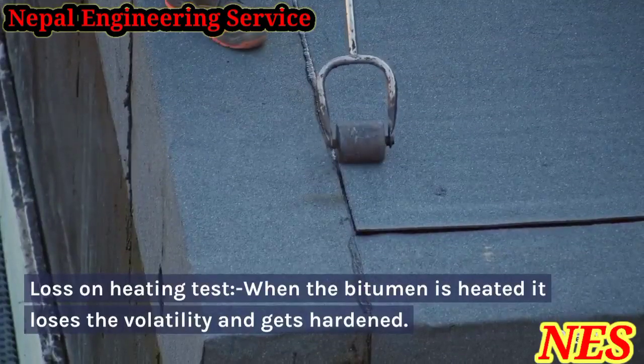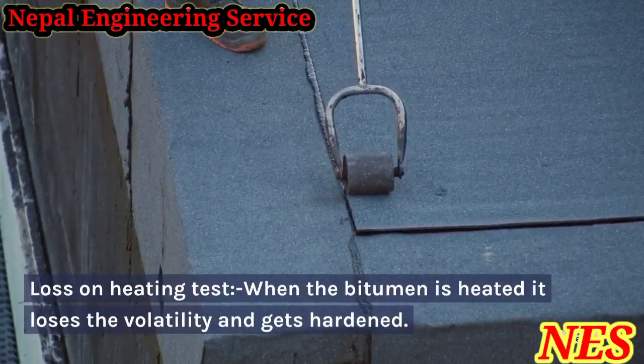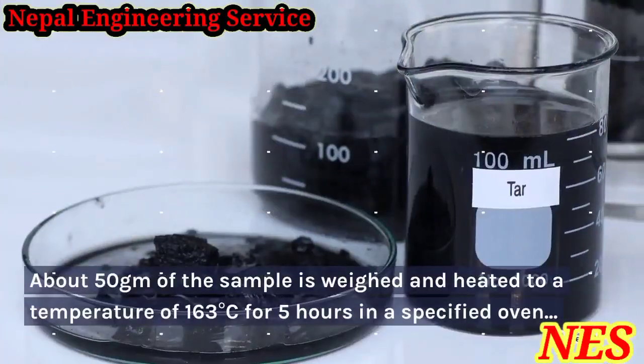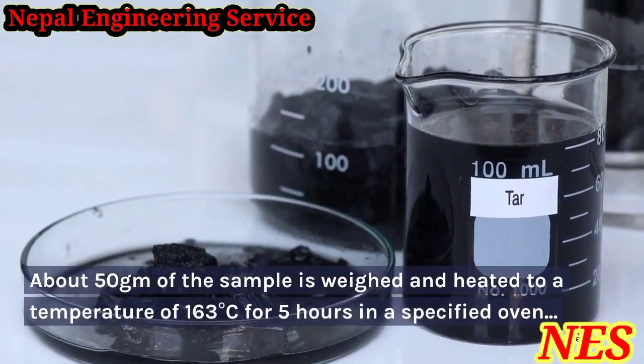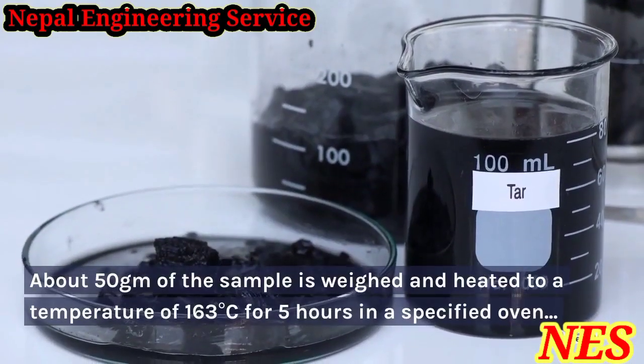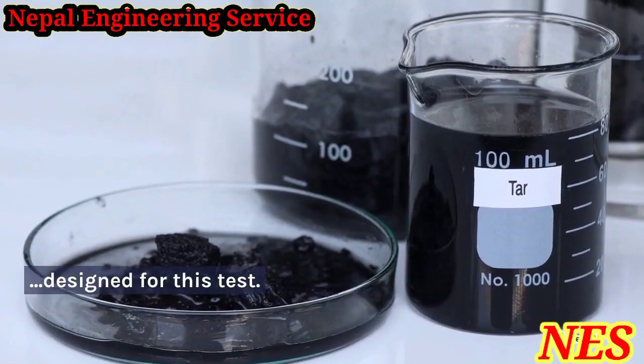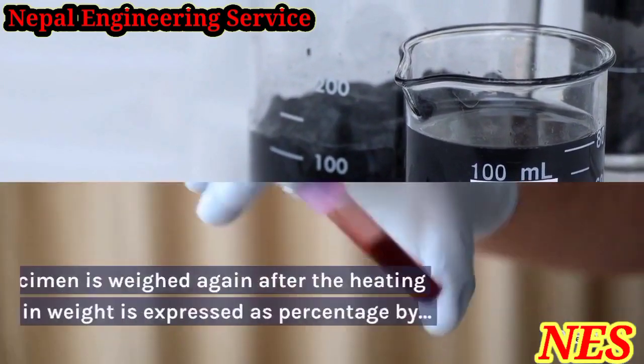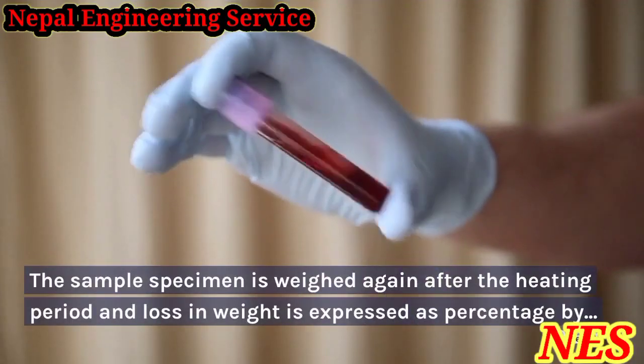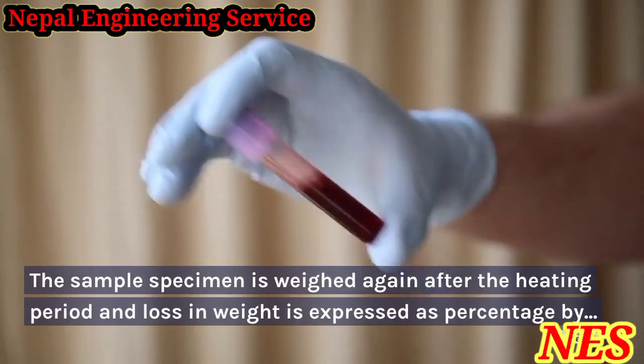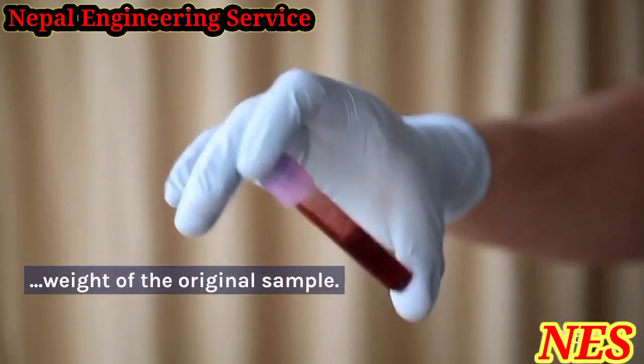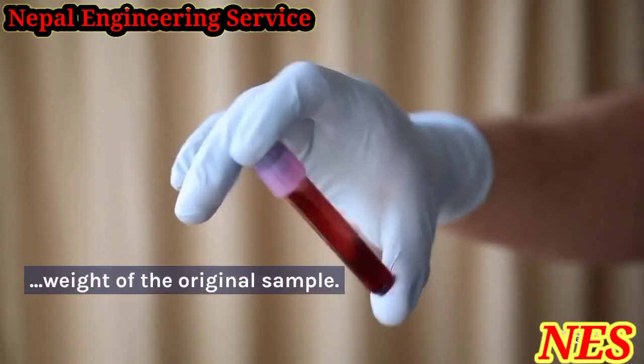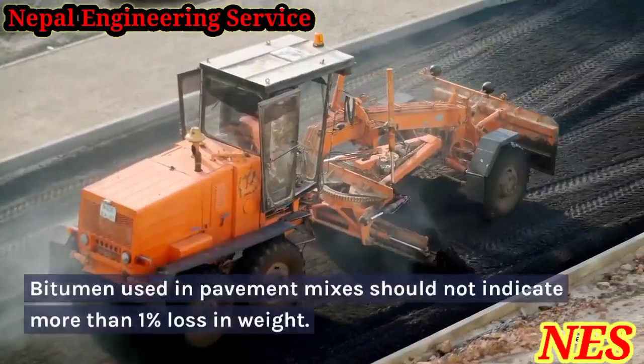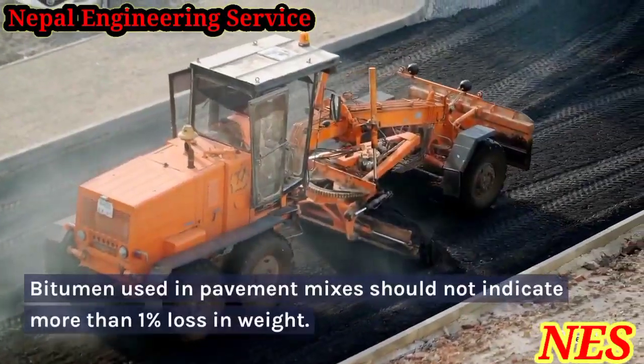9. Loss on heating test. When the bitumen is heated it loses volatility and gets hardened. About 50 gm of the sample is weighed and heated to a temperature of 163 degrees Celsius for 5 hours in a specified oven designed for this test. The sample specimen is weighed again after the heating period and the loss in weight is expressed as a percentage by weight of the original sample. Bitumen used in pavement mixes should not indicate more than 1% loss in weight.